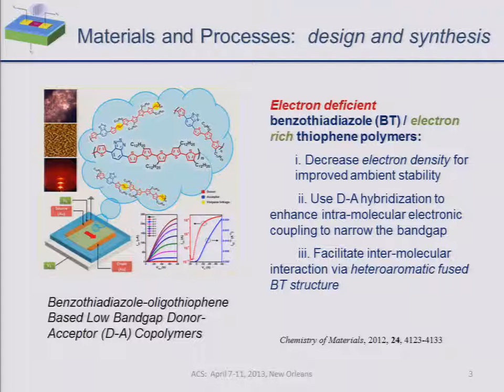All right, so materials and processes. Let's think about what we may be able to do in terms of design and synthesis. On the right is a little bit of a cartoon looking at some polymer structures that have been developed in my own labs where we've been using an electron-deficient benzothiadiazole unit with an electron-rich thiophene unit within a copolymer structure. Through this donor-acceptor copolymer material, we can get decreased electron density that may improve the ambient stability of the material, which is going to be very important for any kind of polymer or organic material to be used in an energy application.